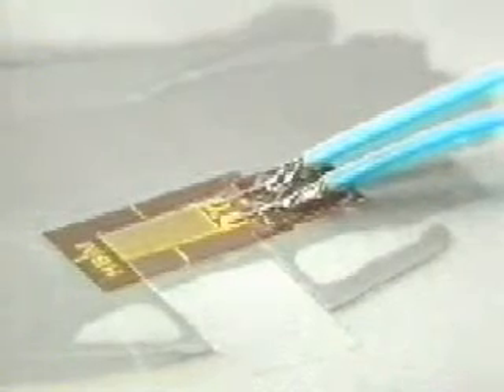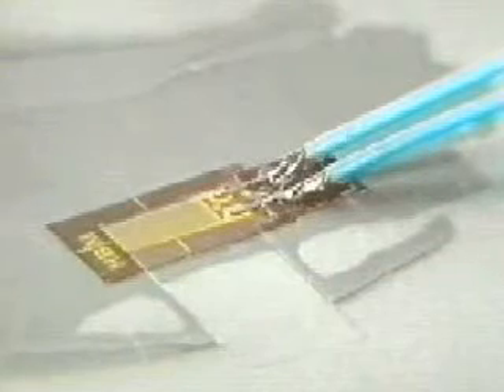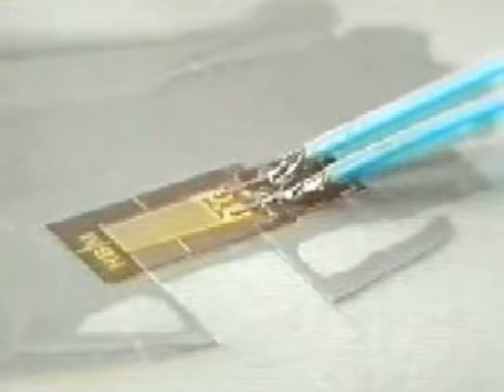Never try to accelerate the solidification by blowing on the joint. This may cause fine cracks in the solder, leading to a permanent fracture of the soldered parts due to temperature variations.